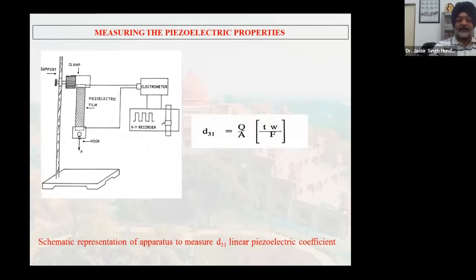So what I am saying is, during measurement of piezoelectric D31, the film is stressed along direction 1, and the charges are measured on the other two faces. So that's why D31, and this is the formula that we use. Q is the charge that develops on the surface, which can be calculated. A is the area of the electrode. T is the thickness of the film. W is the width of the film. F is equal to m into g, that is the weight you suspend.